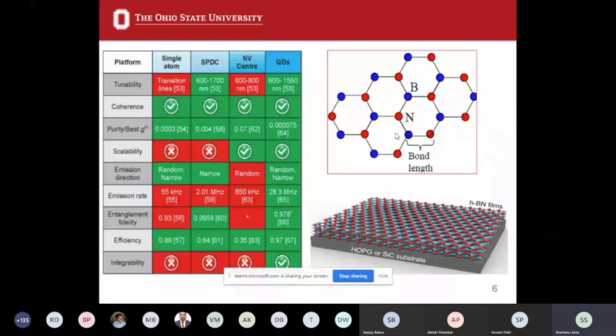Because to get the single photon emission, you also have to take care about the contribution of your substrate. If your substrate has a high absorption coefficient, then that would be of no use, because whatever photon you generate will be absorbed by your substrate. Unfortunately, HOPG may be a good substrate for getting large scale hBN thin films, but it's not good for getting single photon emission because graphite will absorb.